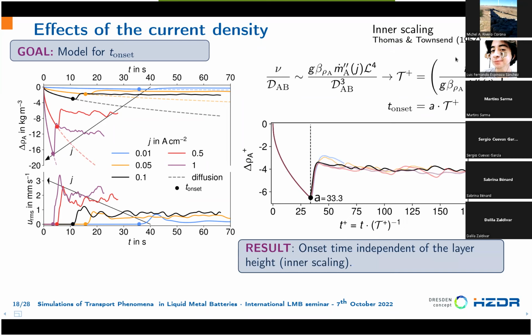We can rescale both the concentration and the time using this inner scaling. And we see that all the curves collapse onto a single curve. This means that this inner scaling is well able to describe what is taking place, in particular at the onset. We see that the onset is now just a constant multiplied by this time scale.